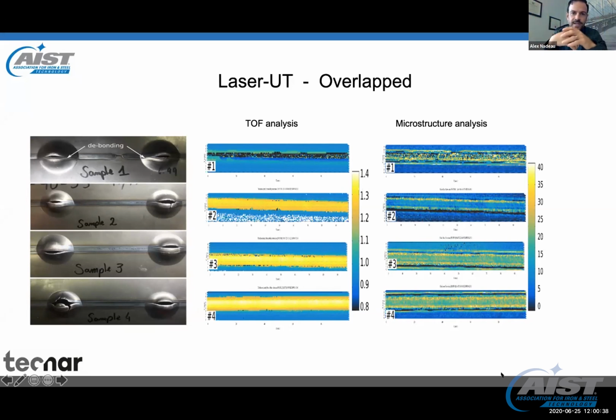So very clearly, just looking at time of flight, there was no sound at all collected in overlap mode for the bad weld. So it was positively working just using time of flight. If we push it to microstructure analysis, we can also see that there was nice recrystallization on weld 3 and 4, but very little recrystallization on weld 2, so probably more brittle, smaller grains, as we'll see later. And microstructure analysis was irrelevant on weld 1 since we had no sound because of the lack of fusion. So next step, we asked our partner, can you produce 10 welds between the parameters of weld sample 1 and weld sample 2 to see how granular is the threshold for determining a bad weld.